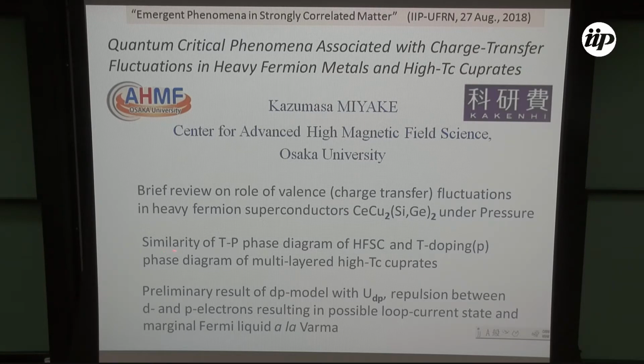Then I'll discuss the similarity of the T-P phase diagram of the heavy Fermion superconductor and the T-doping (p) phase diagram of multi-layered high Tc cuprates. Then I'll show our preliminary result of the 3-band dp model with U_dp, repulsion between d and p electrons, resulting in a possible loop current state and marginal Fermi liquid behavior.